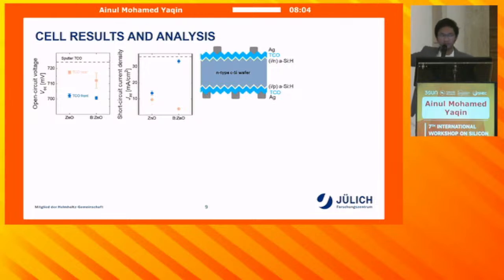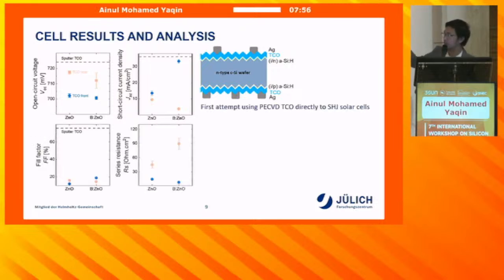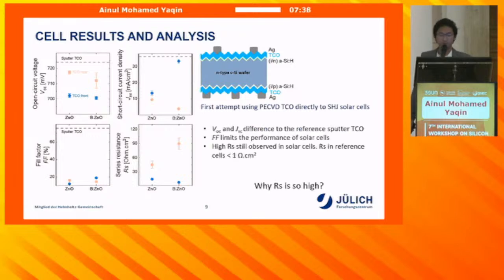We believe that it is because of the relatively poor materials that we have at the moment. As you can see, for example, here we have a very low fill factor, which mainly comes from the series resistance, which indicates that the TCO that we developed with PECVD is still relatively poor. But this is our first time using the PECVD TCO directly on silicon heterojunction solar cells. The question is why the series resistance is so high, even though previously we have shown that the electrical properties are quite acceptable.